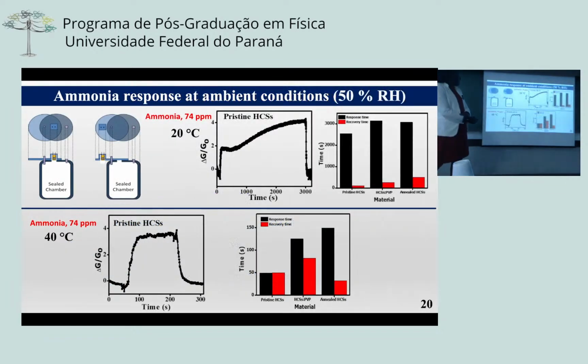We did the ammonia response at ambient condition, which was 50% humidity. The room temperature was 20, and for the pristine, you can see the response here. It takes a very long time to respond, over 2,000 seconds. Even the polymer and the annealed take longer to respond under ambient conditions, with a two-step saturation, because of the slow adsorption due to the presence of defects on the surface. Then we increased the temperature to 40, and you can see the drastic decrease in the response time and recovery time. Ideally, you want a sensor that responds quickly and also recovers quickly.